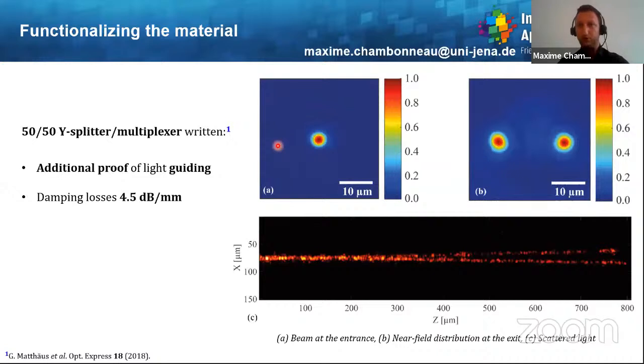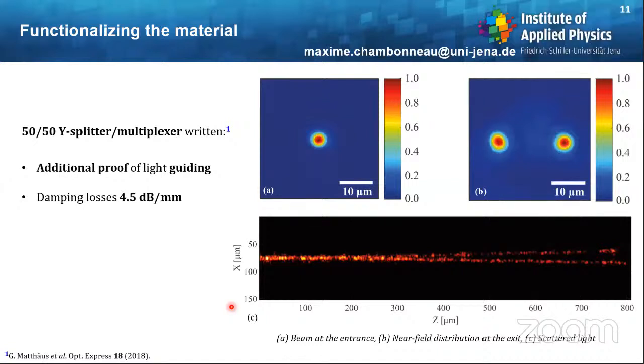It is also possible to not limit ourselves to waveguides, but also to Y splitters, which are often called multiplexers. The idea here is to inject light inside a waveguide and then have two other branches. So the light is split in two. Here you can see on this figure on the right that we have a 50-50 Y splitter, which is an additional proof of light guiding. And the damping losses are on the order of 4.5 dB per millimeter.